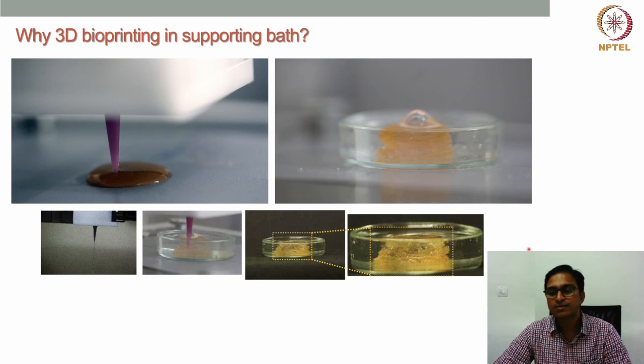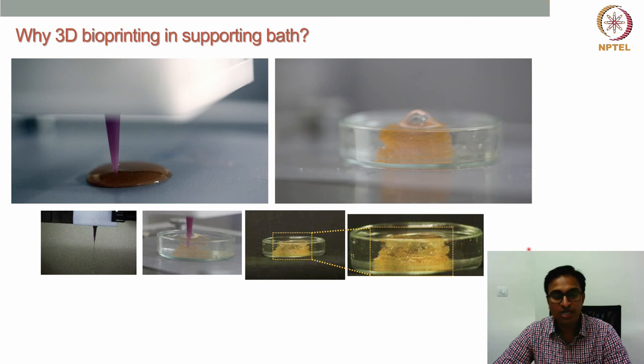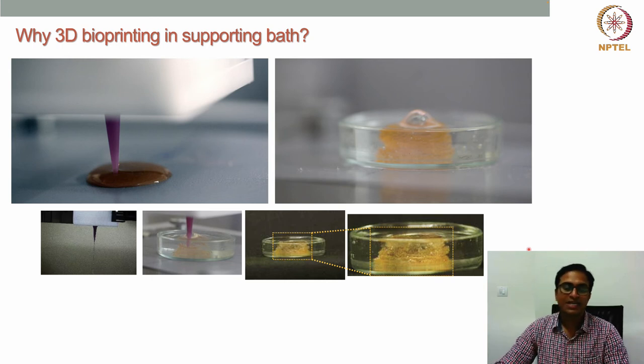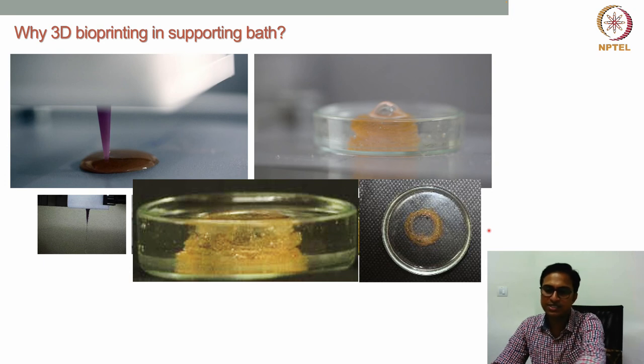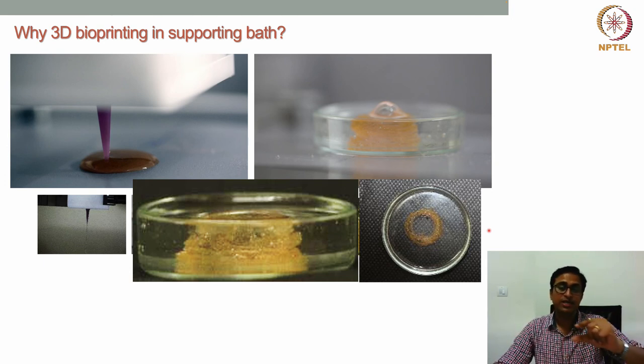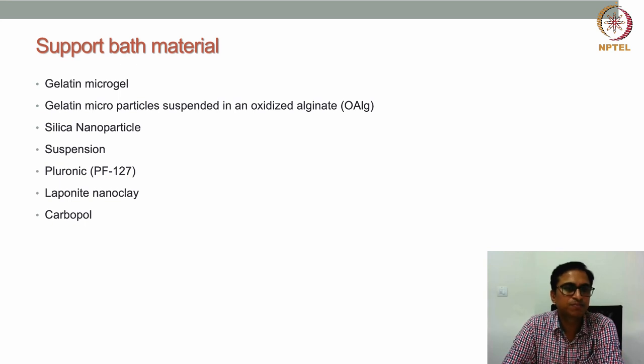People have started using this technology for different applications. A recent important breakthrough came from Tel Aviv University in Israel, where researchers printed a human four-chamber heart-like structure using a very soft hydrogel with 3D support bath bioprinting. The printed structure had all the walls and chambers, with architecture very similar to real heart tissue. Cylindrical structures of 5–6 mm height or more can be created with this support bath approach, which is not possible with conventional bioprinting.